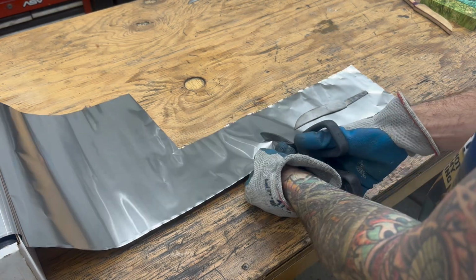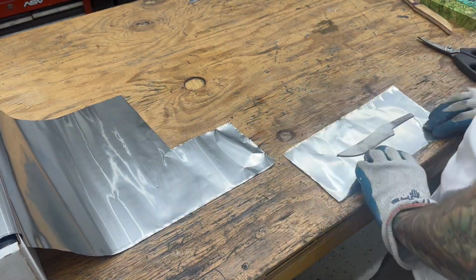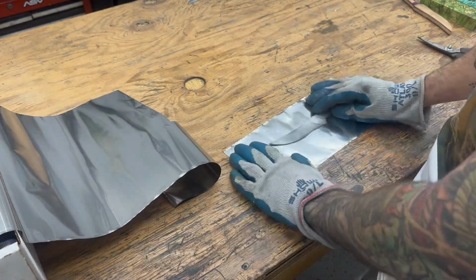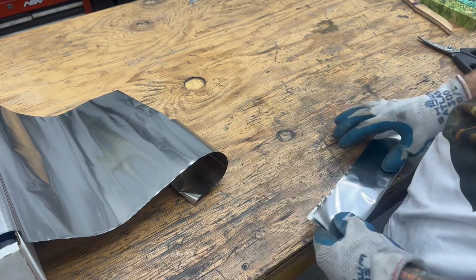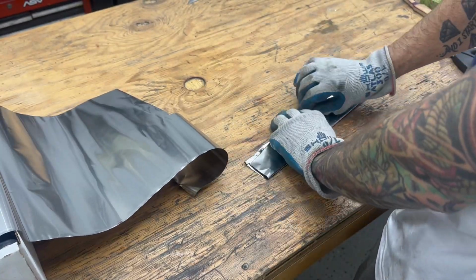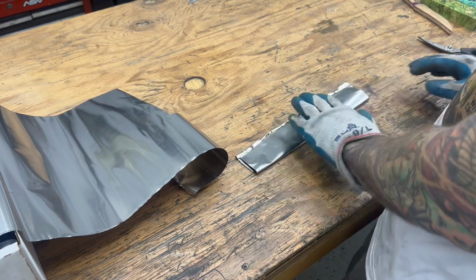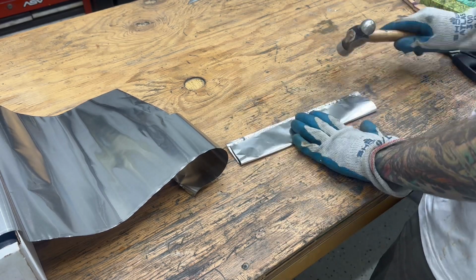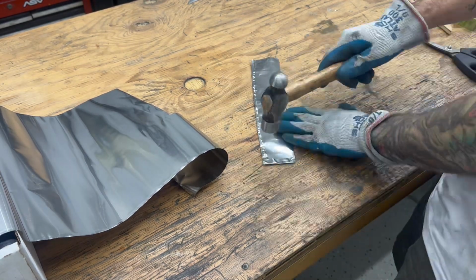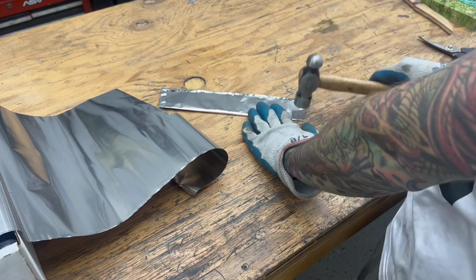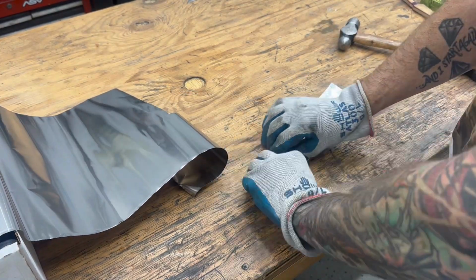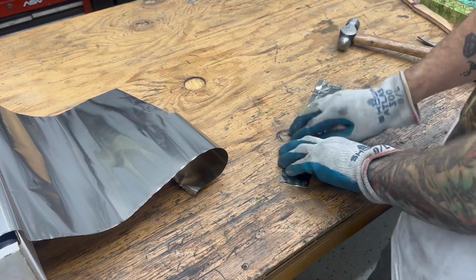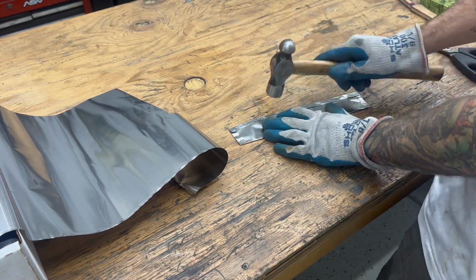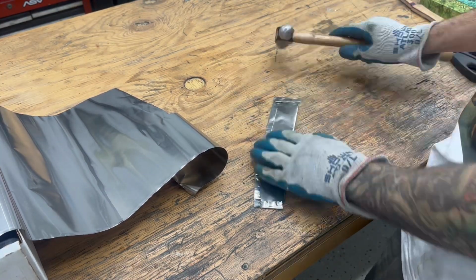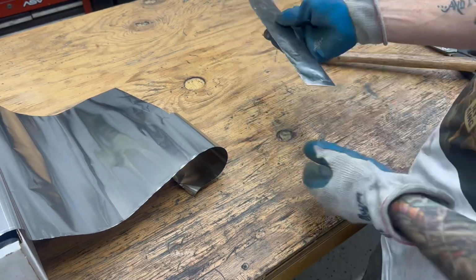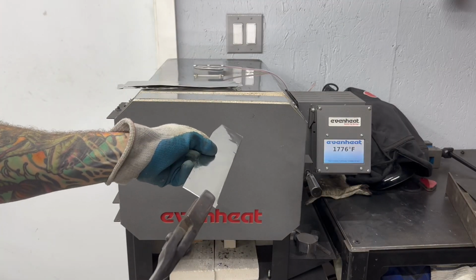It's something you have to do when doing stainless steel to keep the oxygen off of the knife, because unlike carbon steel or high carbon steel, stainless at these extreme temperatures really wants to oxidize, and you'd have to grind quite a bit off if you didn't do this process. So I have this stainless pack, and I make these little pouches, just folding over a few times to get everything airtight, and then into the kiln for heat treat.